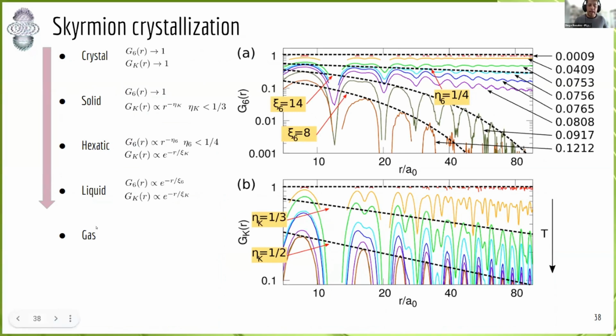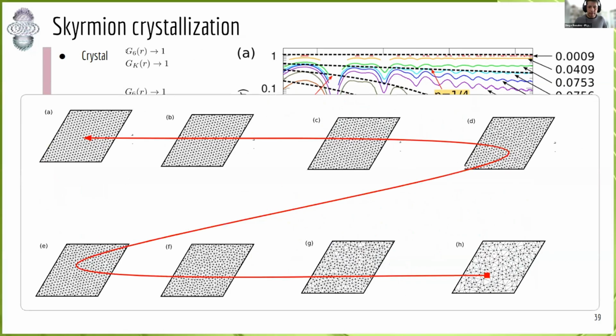The first one, at high temperature, is a gas of skyrmions, and then a liquid with this characteristic behavior in the correlation function. Perhaps an intermediate, in a very small window, a hexatic phase of skyrmions, and then solid or crystal. Okay, this is basically the idea. We start in a gas with a very small density of skyrmions, and then we finish in a skyrmion crystal.